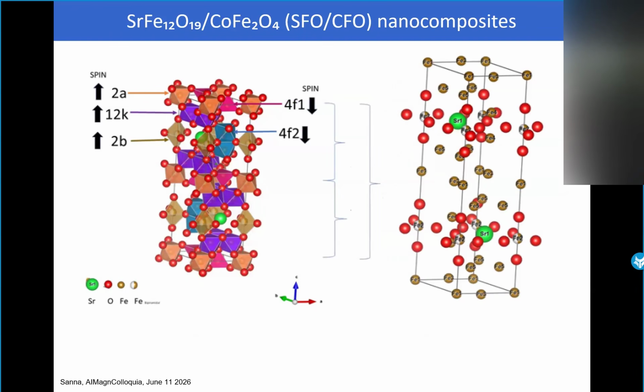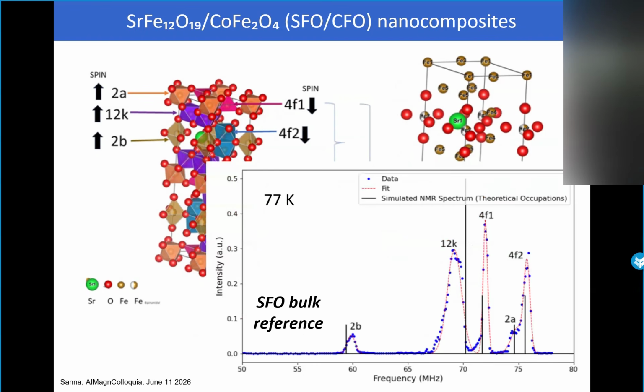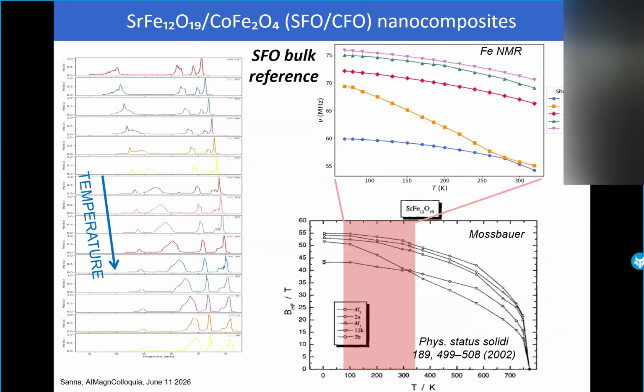And in these materials, as Nader already pointed out, we have 5 different inequivalent iron sites, which are reflected in 5 different hyperfine fields, because each iron site has its own hyperfine field. And this is the spectrum for the reference pure SFO bulk material with these 5 different peaks related to each of these crystallographically and magnetically inequivalent sites. We are going in the next to mainly consider these peaks, which are the most intense.